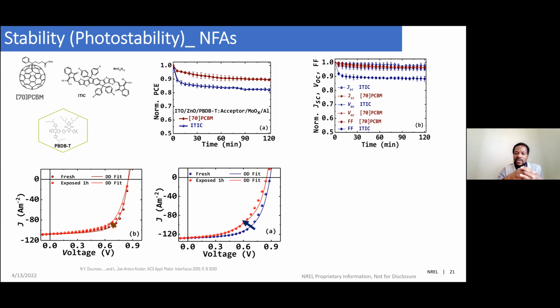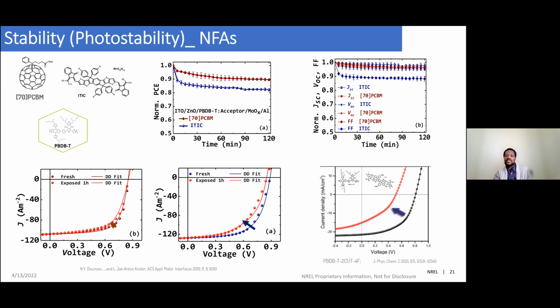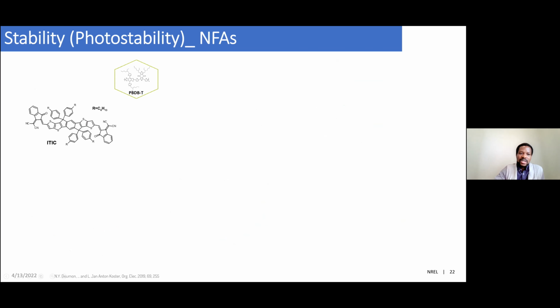the loss due to the fill factor is coming from the mobility, the changes in the mobility and charge imbalance in the system. So as you expose this for a longer time, you lose this much more in your mobility, and therefore your charges become imbalanced in the system. And this has also been an observation done by Abdulaziz et al., where they look at another system based on the ITIC and expose them for 10 hours, and then you can see that this effect is even more pronounced here.